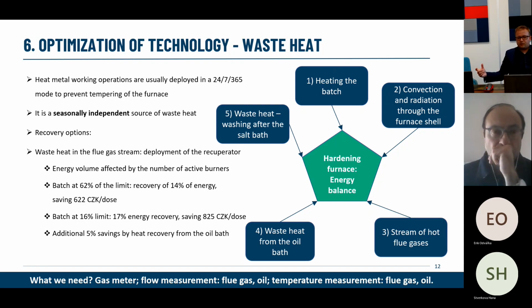There is an oil bath. So when you finish the cycle, you dip that very hot chunk of steel into oil so that you do the tempering. You relax the stress in the steel so that it gets a combination of hardness and toughness eventually. It's actually an interesting process after all. And there's also a salt bath in one of these devices. Part of the technology, you need to wash it to get rid of the salts. In one case, you bathe it in oil, in another case, in a special salt liquid. So every time you can capture heat.